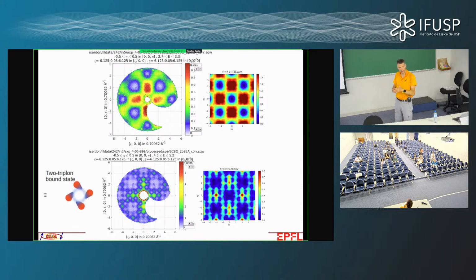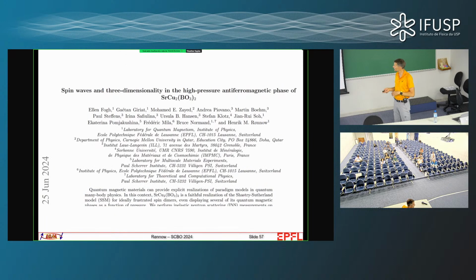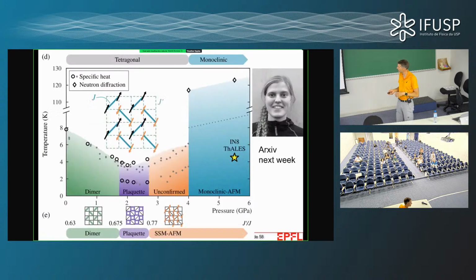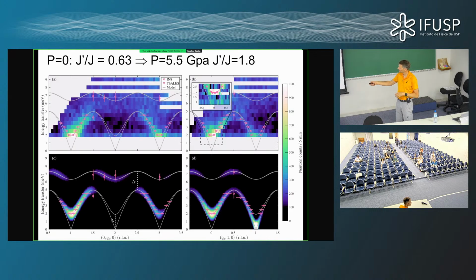In fact, this is now done with a different type of instrument called a triple axis spectrometer, where we really move. We have an incoming beam, we have an outgoing beam defined with analyzer crystals and a single detector, so that we have enough intensity and low enough background. Every pixel in here is actually moving physically, the analyzer and detector, then counting for 10, 20 minutes, then moving again, counting for another 10, 20 minutes, building up this color map here.